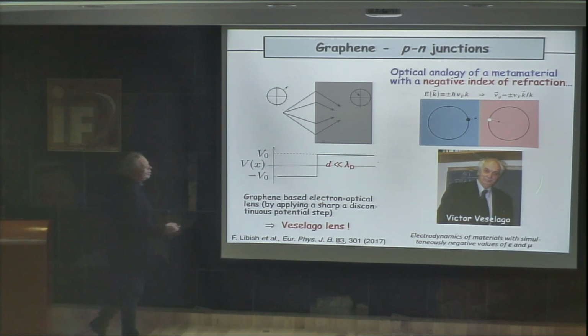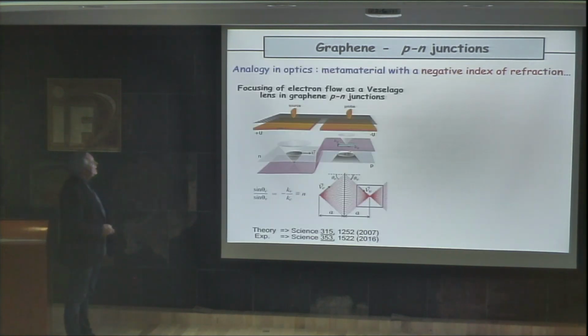And this was first studied by a Russian physicist, Victor Veselago. That's why we call it the Veselago lens. Okay? This effect was predicted theoretically first in graphene in 2007 and has also been observed experimentally in Science in 2016. So just by putting two gates with different voltage, different potential, you can create this p-n junction, and if your interface is sufficiently abrupt, you can really observe this focusing of the electron trajectories of the Dirac fermions in the system.